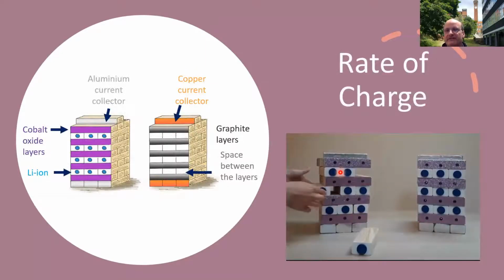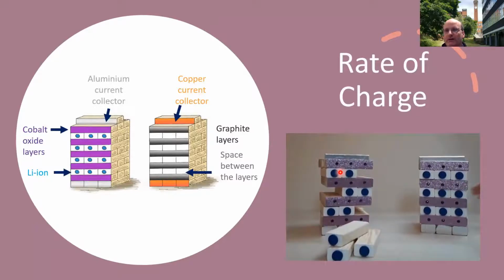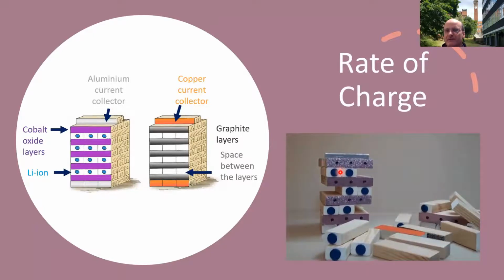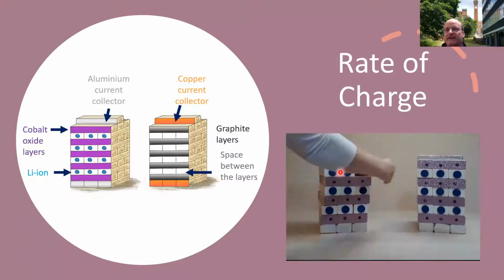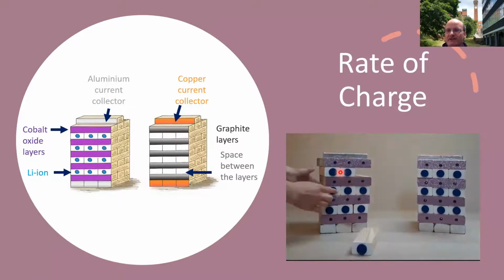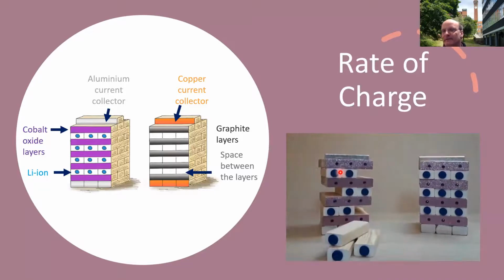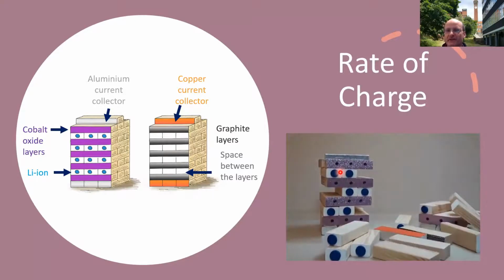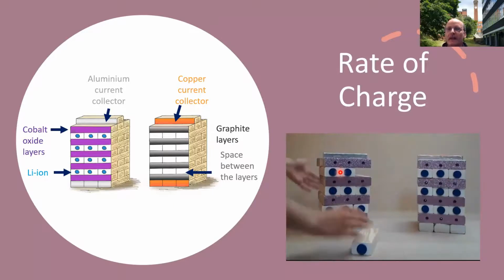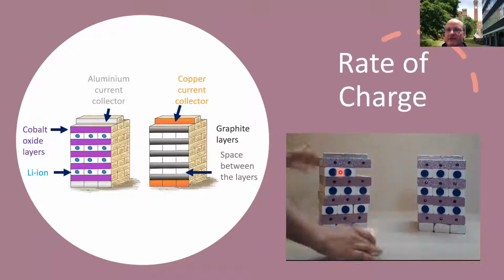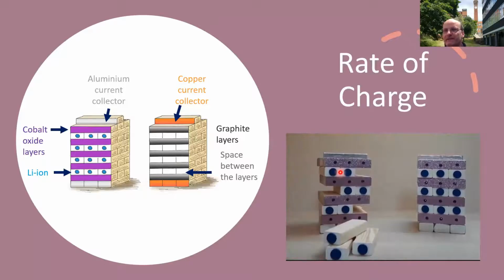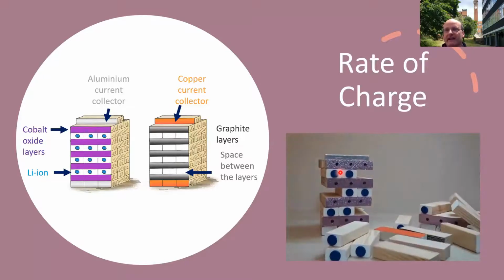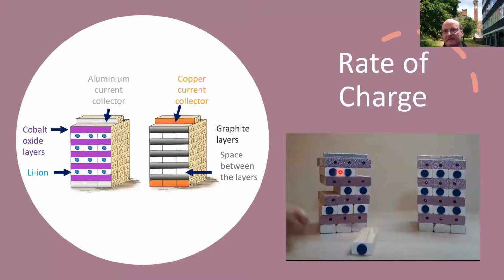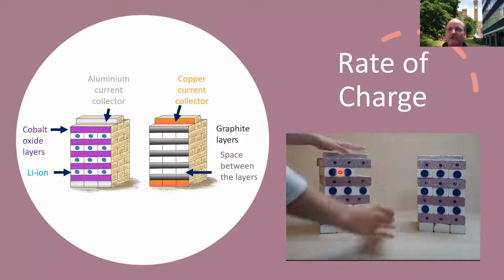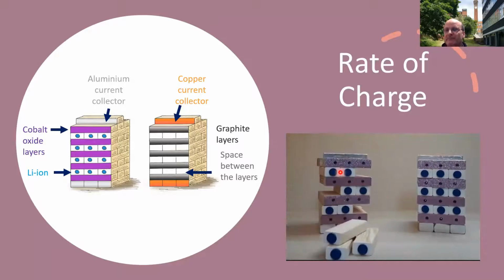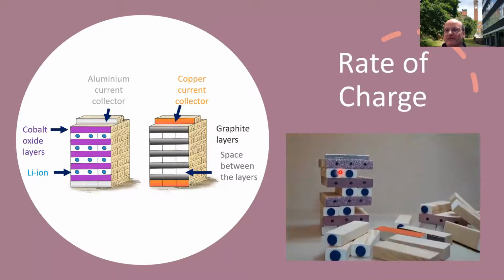You can also try to explain to a certain extent why there are challenges with charging these materials. Like Jenga, if you're taking a block out, you tend to do it quite carefully to make sure you're not knocking everything about. It's similar when you're charging your battery. You want to remove the lithium quite carefully, quite slowly, which allows the structure to relax as the lithium's removed. If you try to remove it too fast, you can potentially damage your material.